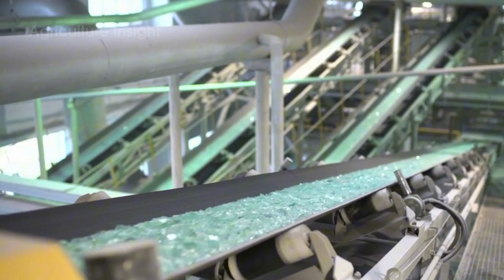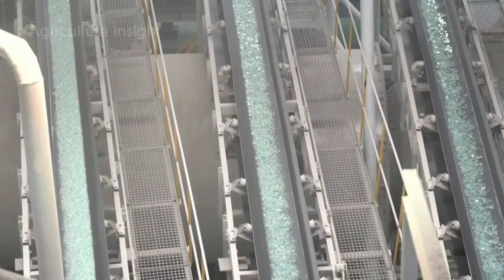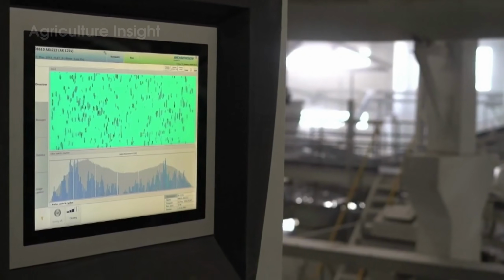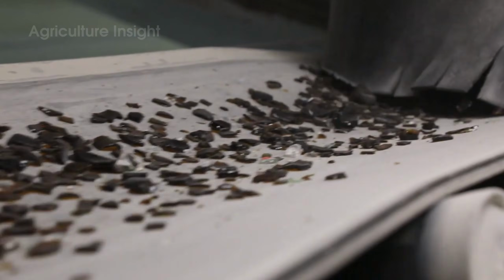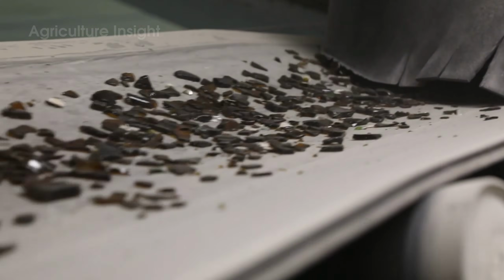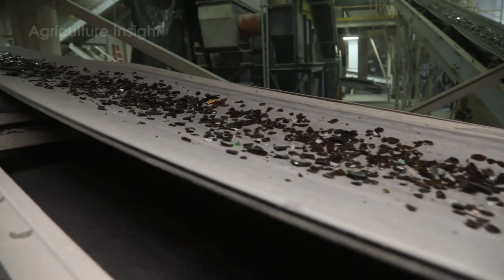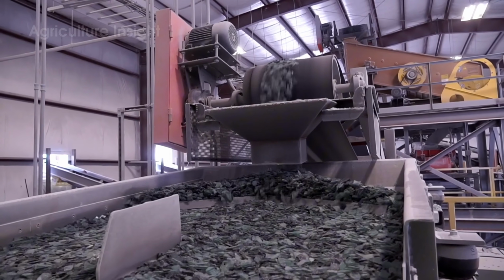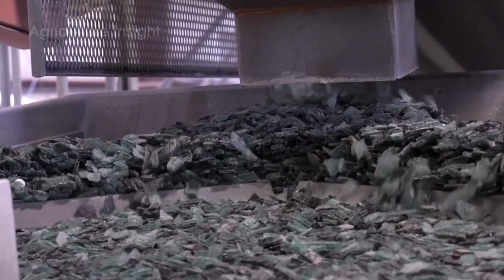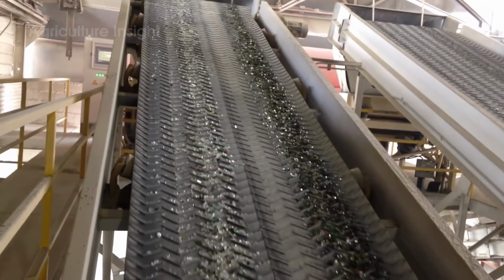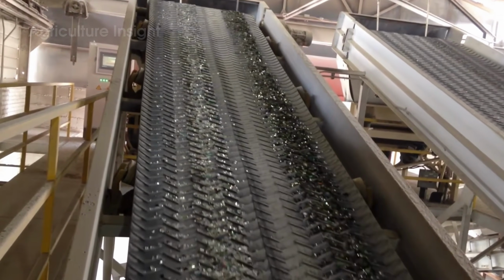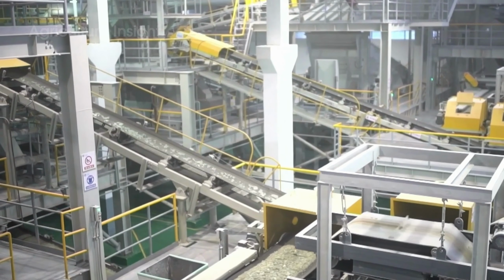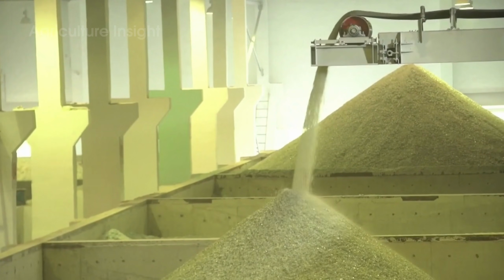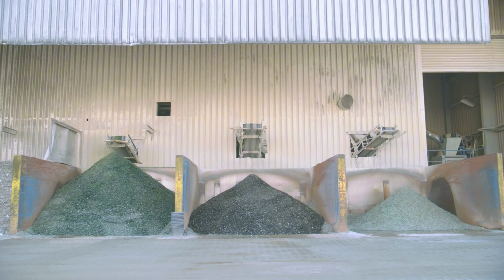After passing the laser system's inspection, the clean glass fragments move along the conveyor belt to the final collection area. Here they are separated and stored individually according to 3 color codes: clear, green, and brown. A step that may seem simple, but in fact directly determines the value and efficiency of recycling. Few people know that clear glass accounts for the largest proportion and has the highest economic value. However, with just 1% colored glass mixed in, a melting batch will immediately become cloudy and unable to regain its original transparency. Therefore, color separation is mandatory to control purity, enabling factories to recycle directly into new products of the same type without incurring the cost of removing color impurities.